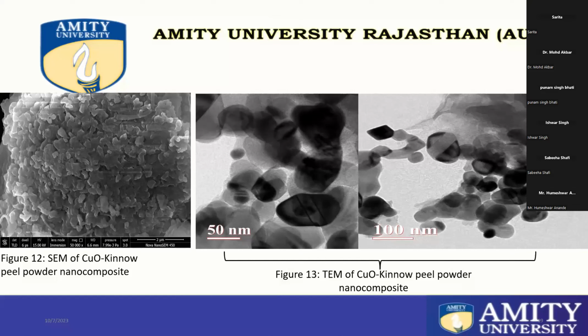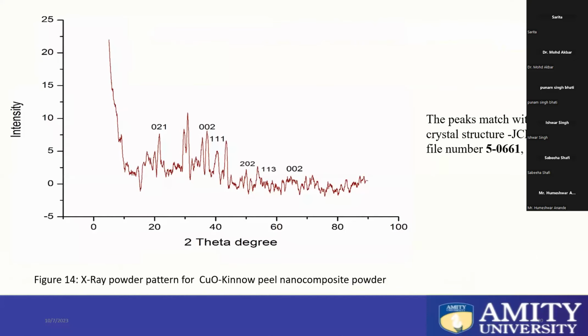The study shows that yes, the particles have been formed at nanoscale. The image shows that it is a spherical agglomerated compound, and the same image shows that it is in the range of nanometer scale. After the catalyst has been formed and characterized, XRD also shows that it has a crystal structure matching with copper oxide with reference to JCPDS file number 22.